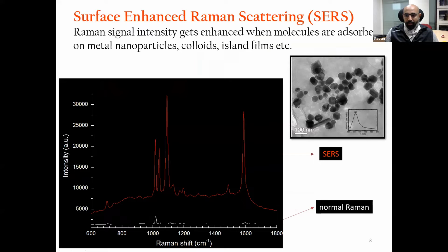Now, one of the consequences of creating such gaps is that you have a molecule which experiences enormous optical fields, and the molecule happens to be a Raman scatterer which has a relatively weak Raman cross section. For example, if you take a thiophenol molecule and you adsorb those molecules onto the nanoparticles shown in this transmission electron microscope image, in conventional normal Raman scattering you get Raman modes associated with the modes of vibrations of the thiophenol molecule. The moment you adsorb these molecules onto metallic nanostructures, you get enormously enhanced Raman scattering signatures.